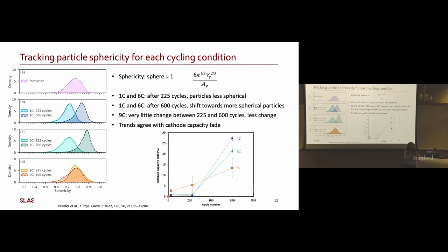Well, we think as you get smaller particles, at first those cracks, you're just breaking apart a big particle, and those cracked particles are not very spherical. But then those fractured particles further fracture, and they fracture into something that's more spherical.